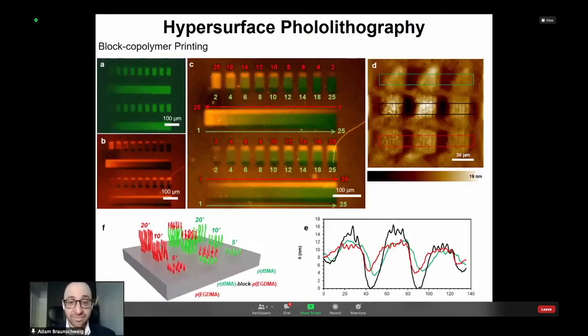But one thing that we managed to do that you can't do with any other printer is the following. Here what we did was we printed block copolymer arrays where the height of the overall polymer and the length of each of the individual blocks within the polymer is also precisely controllable. So here you see a feature of constant height where these numbers correspond to the different growth times. Constant height because here you're decreasing red as you go from right to left and increasing green. Or here what you can do is increase both together. The point is arbitrary patterns but complete chemical control in the system.